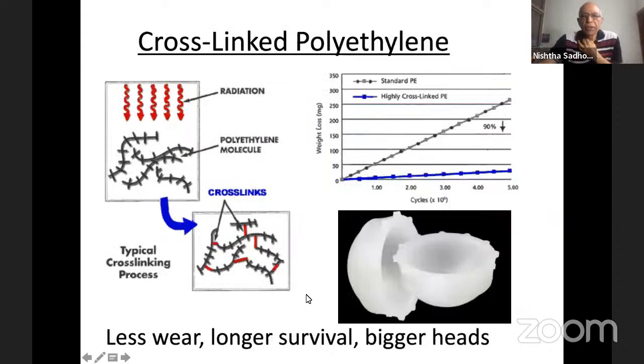So now we come towards what I think is probably a good compromise, the cross-linked polyethylene. The one thing against the conventional poly was that it produced a lot of wear. Its life was somewhat restricted as compared to other bearings, so it fell into disrepute. So the engineers got around this by so-called cross-linking. That is, they give gamma radiation, and the two strands link to each other. You see, these are free strands here, and they link. So there's a cross-linking between the two.